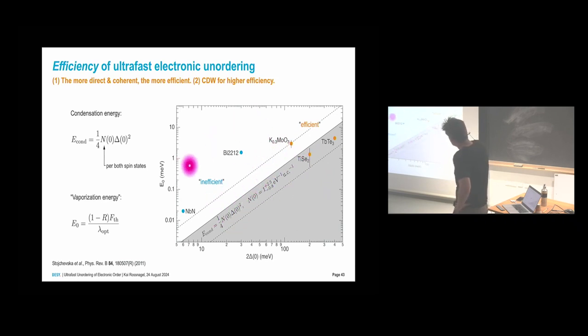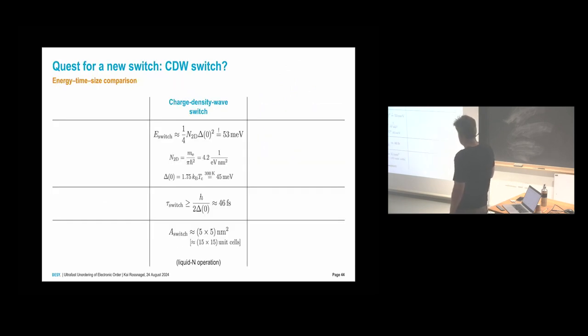Here again, the superconductors are inefficient. You have to put a lot more energy in because you have this indirect, dissipative process, whereas in the charge density waves, via these coherent oscillations or via the electronic screening, you are relatively efficient in killing the charge density wave state. So in the end, if you want to do a charge density wave switch, of course, here's my little caveat.